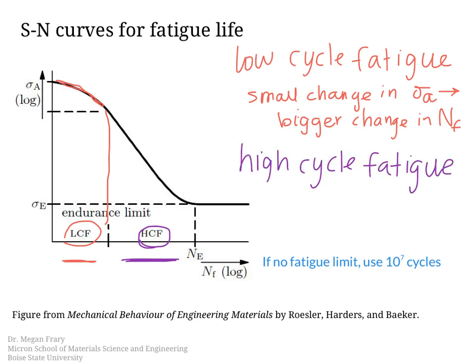As we will see in the following video, high cycle fatigue is typically stress controlled, or the stress is what's the same on each cycle, and low cycle fatigue is usually driven by a strain controlled deformation. And we'll go into why that is and how these curves look in more detail there.